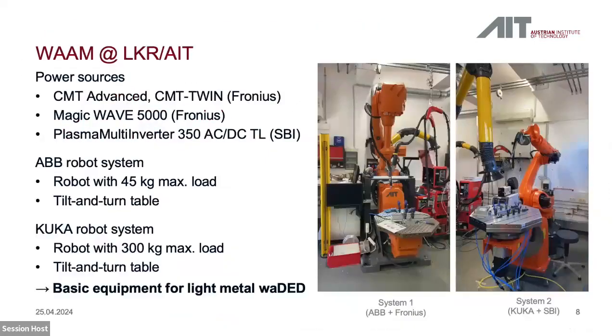Of course, we have to have a system to handle the torch. These are the two operating systems we're using. One ABB robot, one KUKA robot. And they allow us to build up complex structures with light metals. What is not shown here is, of course, for titanium, we have to have an enclosure to avoid oxidation. We have developed a chamber that is suitable for the robotic system, and that is currently turned into a product by one of our partners.